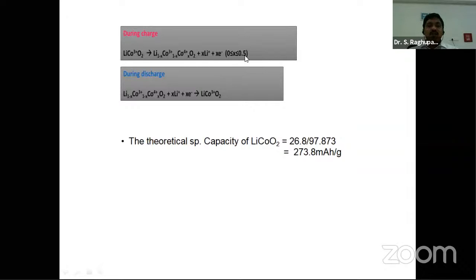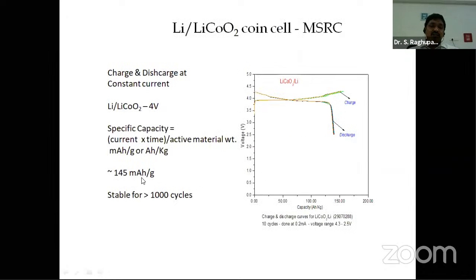If you go beyond 0.5 lithiums, LiCoO2 loses its crystal structure and converts into a different crystal structure. Finally, it's collapsing its structure. So again, during the discharge, it's gaining lithiums and it will become LiCoO2. The theoretical specific capacity is 273, but we have achieved only 145 milliampere hour per gram. This is the contribution of J.B. Goodenough. He just changed the material and we are able to achieve a very high voltage and capacity material